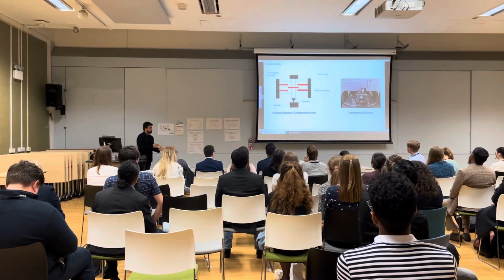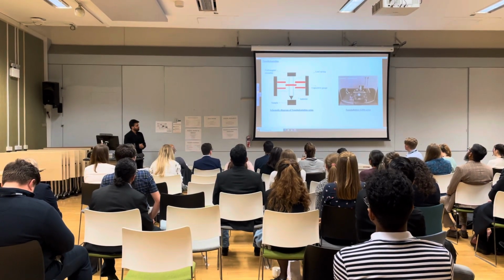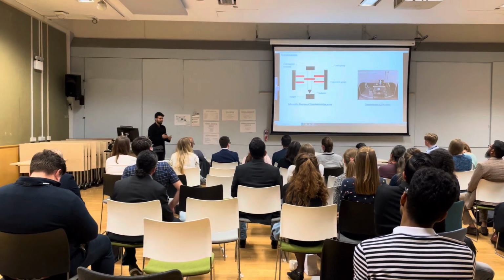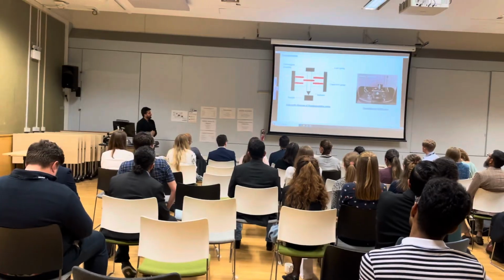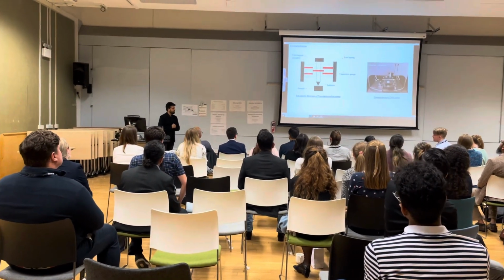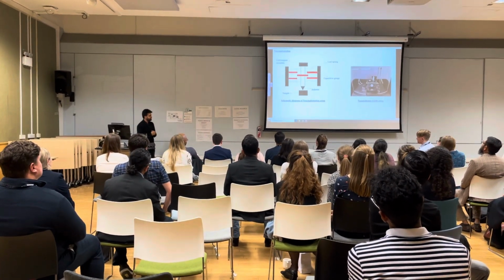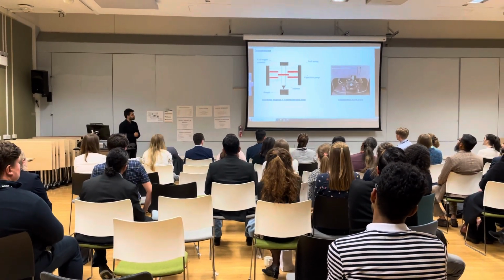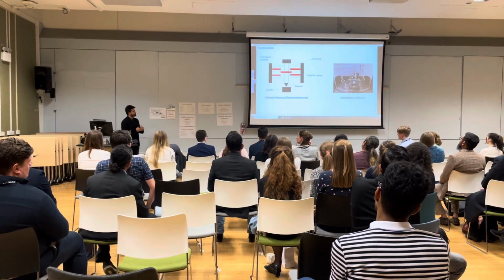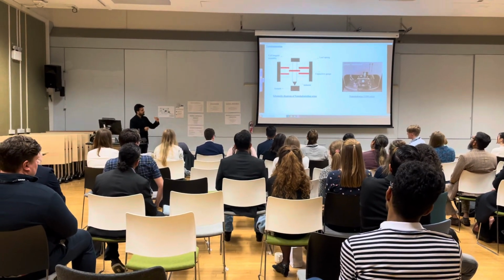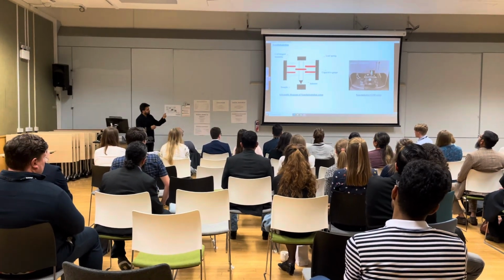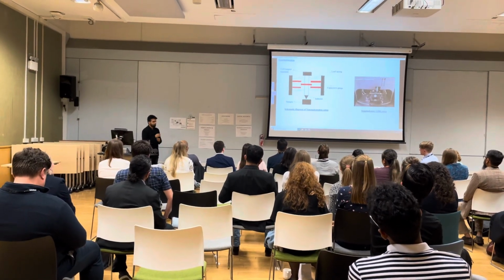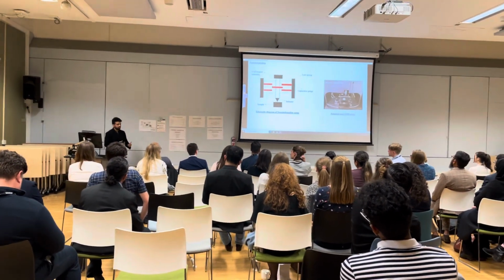Once we performed the rheological experiments, we were also very interested in understanding the properties at the microscale, and that was the reason a nano-indentation test was performed in Liverpool. This is the schematic diagram of a nano-indentation setup, and on the right hand side you can see the G200 nano-indenter which is being employed here. The concept is very simple. You apply a magnetic flux, and because of it the indenter moves in the vertical direction. Capacitor gauges measure the displacement of the indenter, and depending on the input frequency, you can then get the value of the storage and loss modulus.